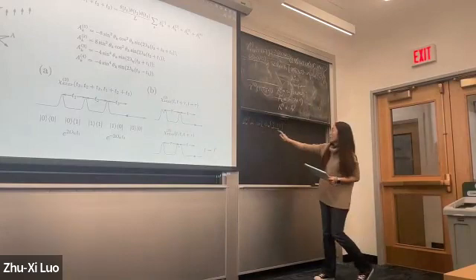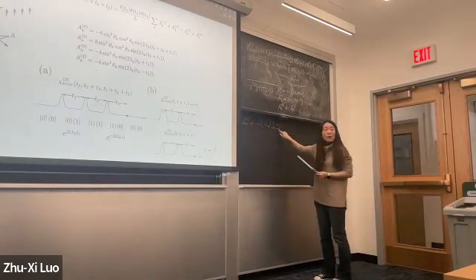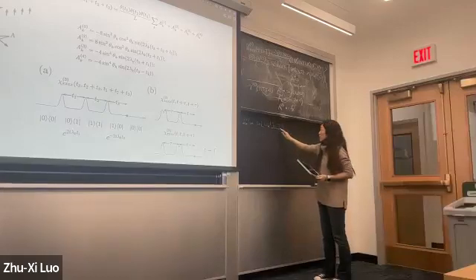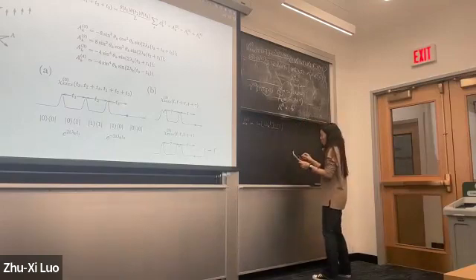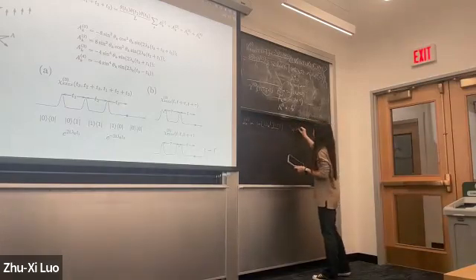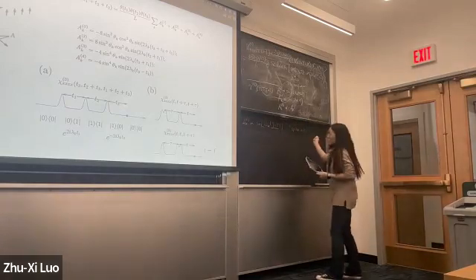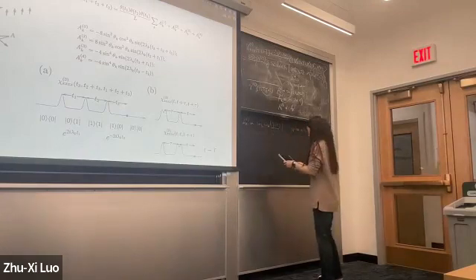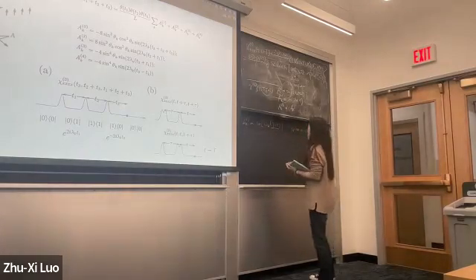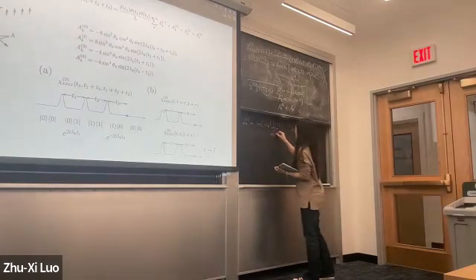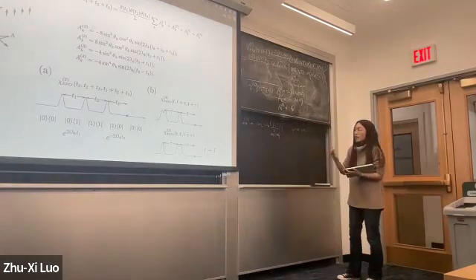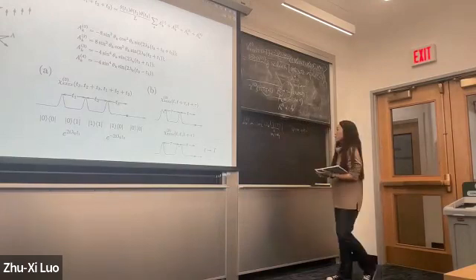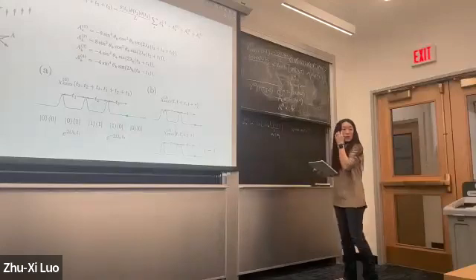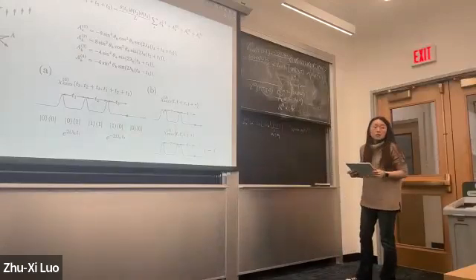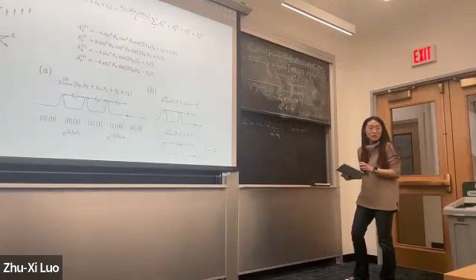Namely, when you have your measurement time, capital T equals tau, you get no phase accumulation. So whatever phase that you accumulated in the first time will be canceled in the end. So that's why people call this spinon echo. And this is the echo for arbitrary momentum k. And if you do a Fourier transformation, this will give you omega tau equals omega T. So it's like a line in a 2D frequency diagram. Is this echo specific to the transverse field Ising model or generic? Generic. Later I will mention it is for arbitrary quantum systems.